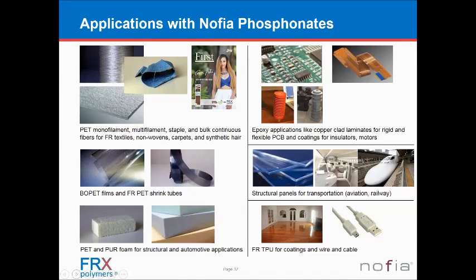So by using our material, you not only can maintain the transparency, but because we are polymeric and we are just part of the polymer phase, you can actually make films that are very thin and still maintain your transparency, but also have your flame retardancy. So this goes down to below 50 micrometers. You can make transparent films out of polyesters that are flame retardant, or for example shrink tubes for batteries. And another application area in polyesters is in polyester foam for structural applications, in addition to, for example, polyurethane foam, where we can be used with our reactive oligomers, where they react with the isocyanates and can be part of the polyols in these types of applications.